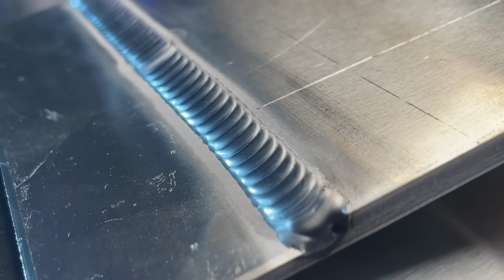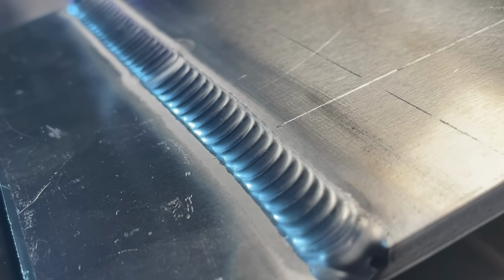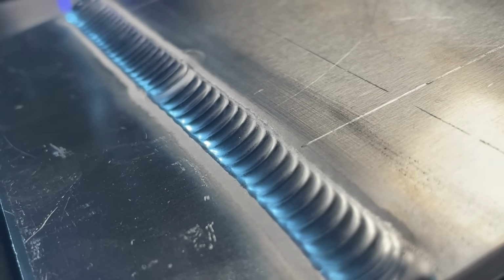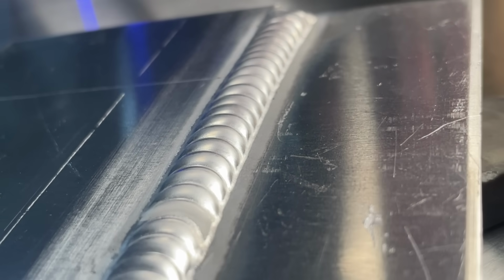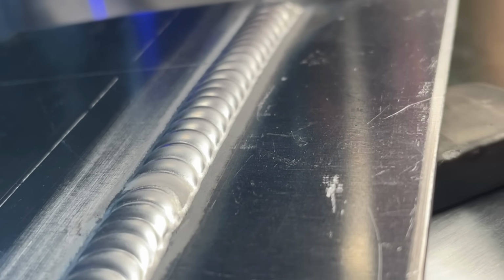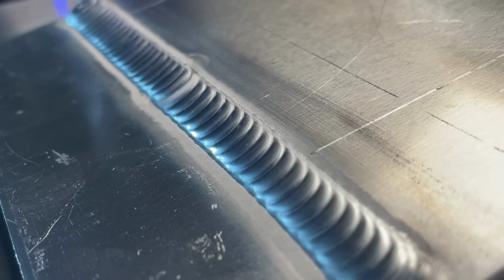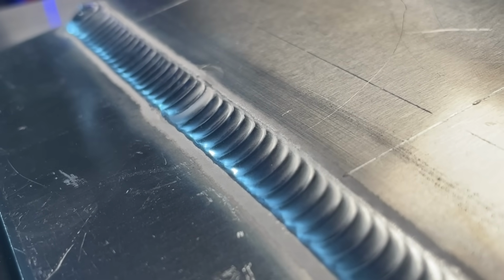Take a look at this example here. We can see at the beginning of this lap joint, everything has been established with perfect size and really good profile. We don't see any overfilling, we don't see any underfilling or overheating. The amount of filler material that I am using here looks pretty much perfect in relation to the amount of heat that I am welding with here.